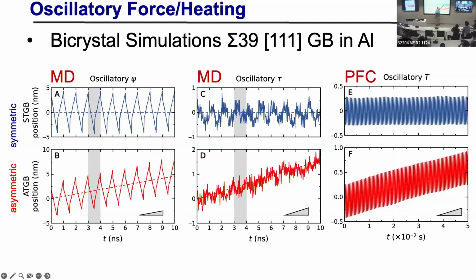And so we do it for oscillatory temperature, in this case. And not much happens. This one, clear migration. You can measure the slope, and that's the velocity in that direction. Okay, so I've shown you stress-driven, chemical potential-driven, oscillatory fields both ways, oscillatory temperatures, thermal cycling.